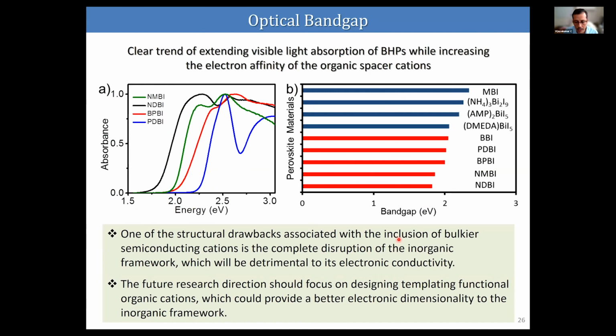And we proved this by using 4 of our materials, and there is a clear trend of extending the visible light absorption of this material to a longer wavelength by using the self-assembling semiconducting organic components. And we were able to get a band gap as low as 1.8 electron volt, which is much lower than most of the reported bismuth halide perovskite reported in literature. Those are represented by the blue ones, and our materials are the red ones.